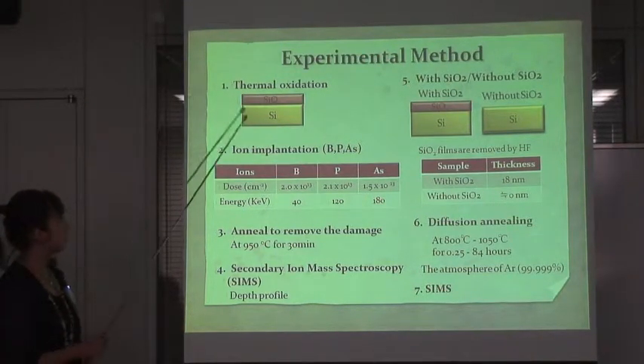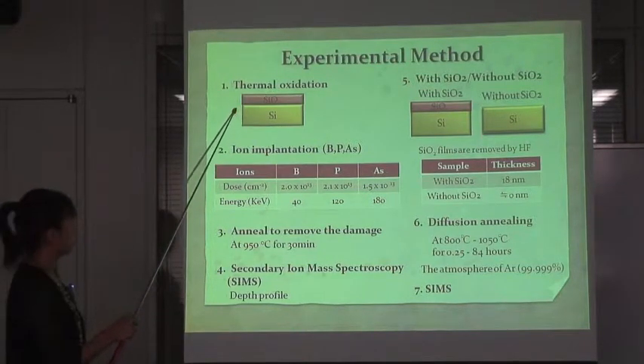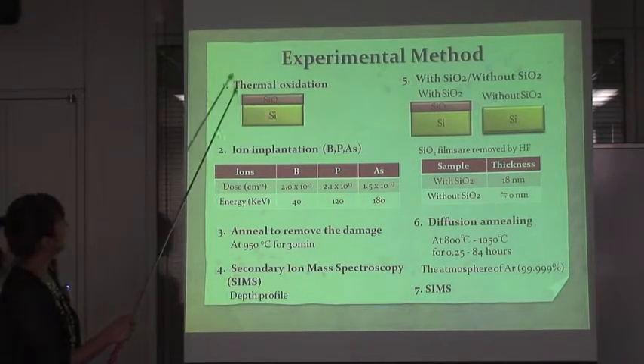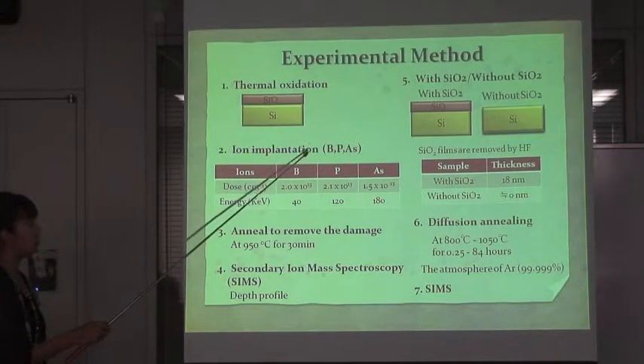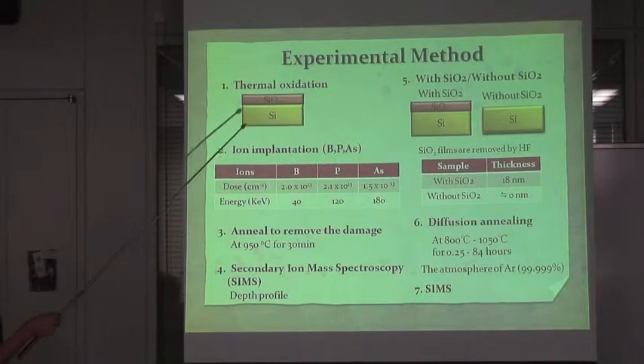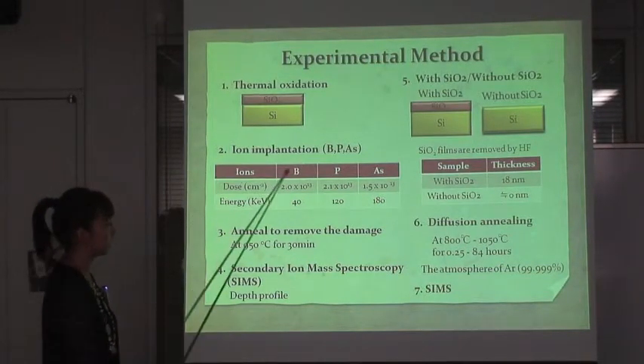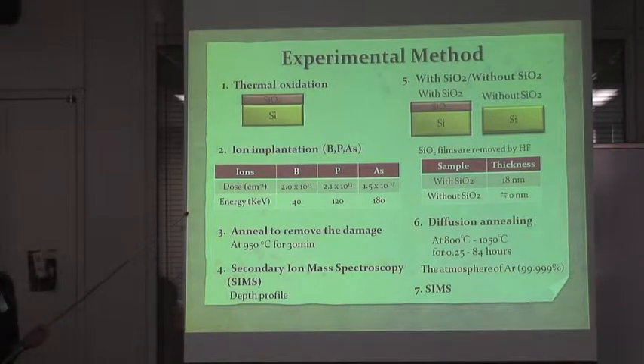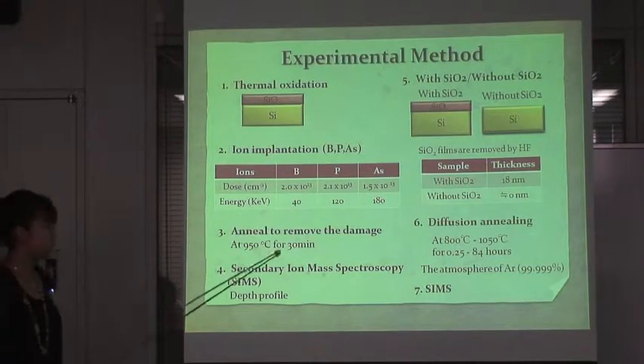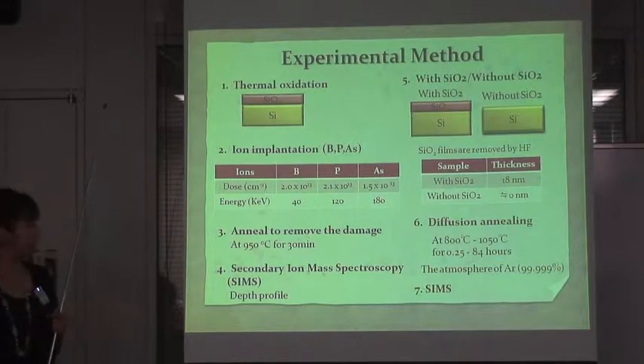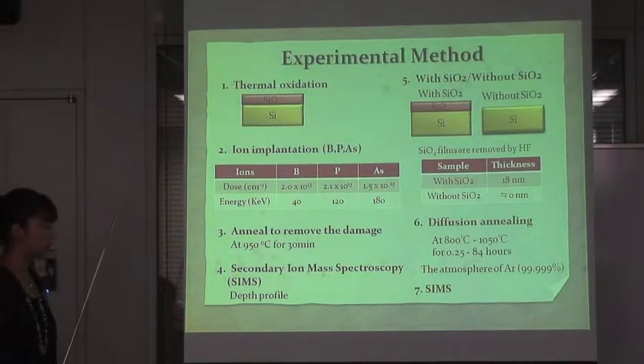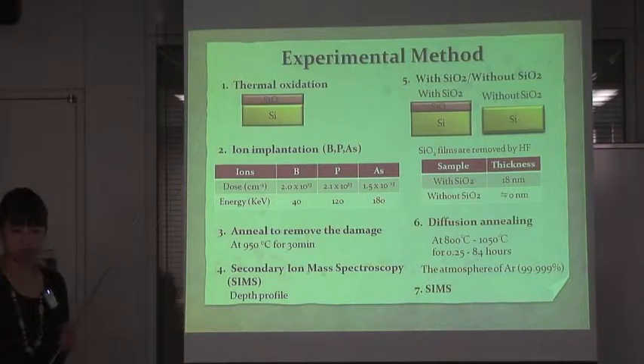First, the samples with silicon dioxide films grown on the surface were prepared, and then boron, phosphorus, arsenic ions were implanted into the samples with the condition as shown in this table. And then samples were annealed at 950 degrees for 30 minutes to remove the damage that would cause a transient enhanced diffusion. And then the distribution of the impurities was measured by secondary ion mass spectroscopy.